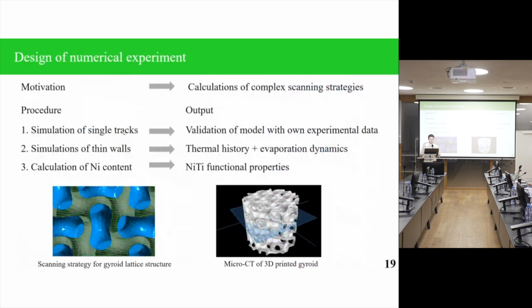The second part of my presentation is dedicated to a numerical experiment, namely the simulation of the melt pool during laser powder bed fusion, and this was done to analyze more complex scanning strategies. In the experimental study, we analyzed the simplest geometry, the thin wall, but in reality we have complex scanning strategies. The laser passes are shown here with green lines, and this scanning strategy rotates from layer to layer. So in this case, analysis of local shift in transformation temperatures will be complicated.